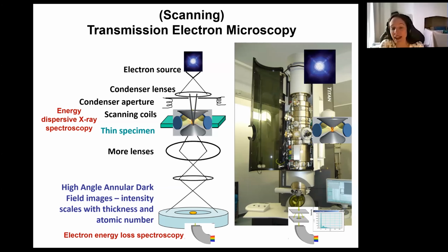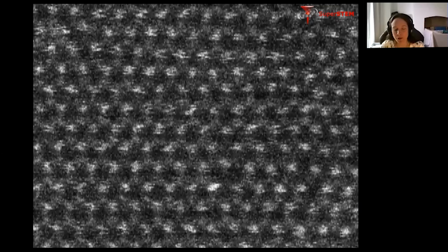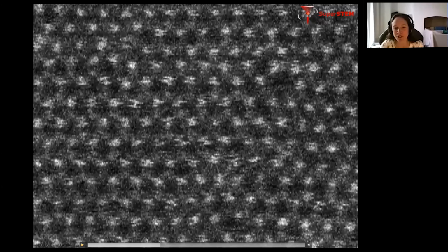And we can also collect the X-rays that have been emanated when the electrons interacted with the material. These X-rays are characteristic of the elements in the sample. So this is an example of a high-angle annular dark field image. I think this one is credit of Recep Zan and Quentin Ramasse at the SuperSTEM laboratory. If I just pause it now, you can see the image is being built up pixel by pixel. You can see the scanning, there's been no correction or anything here. And we can see that these regions of bright intensity are the molybdenum columns, so they're high atomic number, and in between them we have these double sulfur positions.